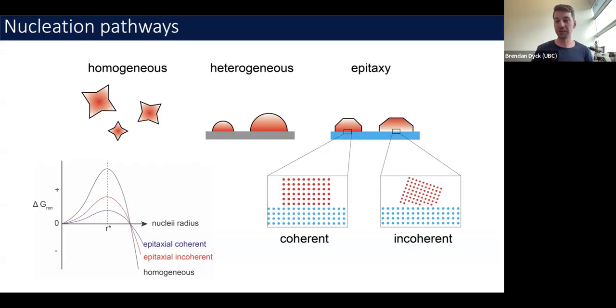Heterogeneous nucleation reduces that energy penalty because there's a substrate that we nucleate on, and it reduces the amount of surface area that actually has to form for that nuclei. Whereas epitaxy reduces that free energy or that barrier energy to nucleation even more. But again, it's a scale from incoherent all the way down to coherent, being a very, very low barrier energy. So with this in mind, we might expect that metamorphic rocks that are slowly progressing through their reactions are always going to develop epitaxy, or nucleation will always occur in an epitaxial manner, right?